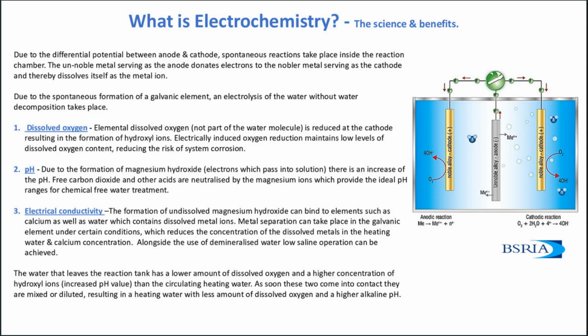So again, following the 1, 2, 3 principle, dissolved oxygen: elemental dissolved oxygen, so that's not part of the water molecule, is reduced at the cathode, resulting in the formation of hydroxy ions. Electrically induced oxygen reduction maintains low levels of dissolved oxygen content, reducing the risk of system corrosion. The pH. Due to the formation of magnesium hydroxide, these electrons pass into the solution. There is an increase of the pH.